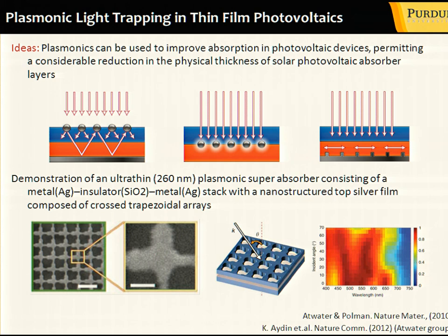I should say, though, that photovoltaic elements are already extremely efficient. If you speak of silicon, they're already getting close to the Shockley limit, and there are already demonstrations of very thin crystal solar cells with efficiency of about 29%, but the field is so important that even if the increase would be just a few percent, it could make a huge difference for the field. And of course, the key element in all these photovoltaic elements is to have very efficient absorption.